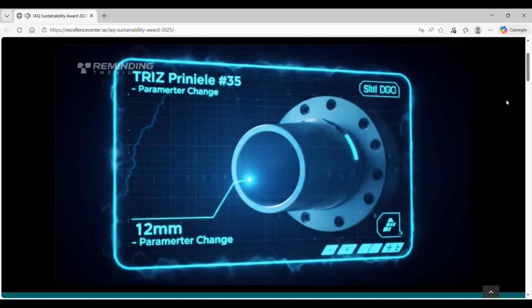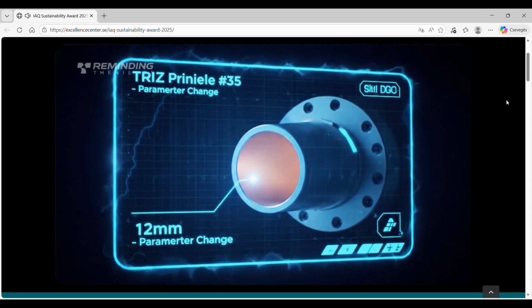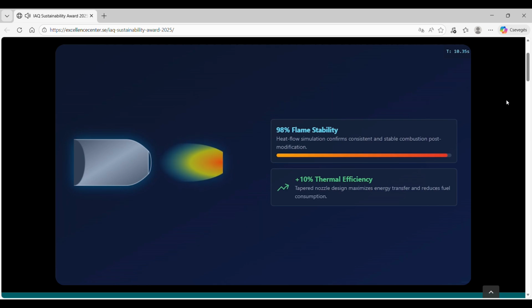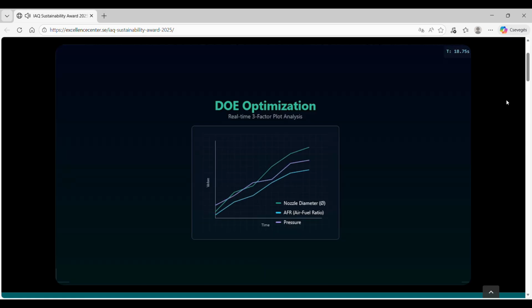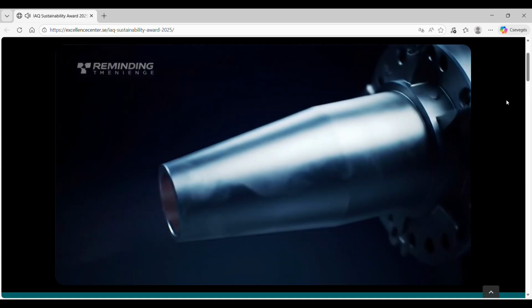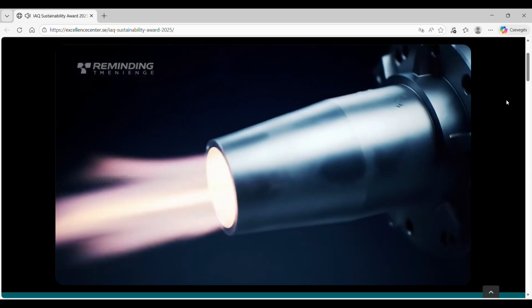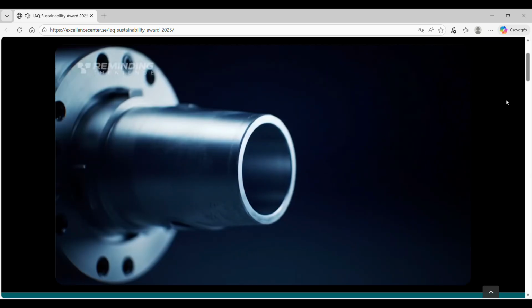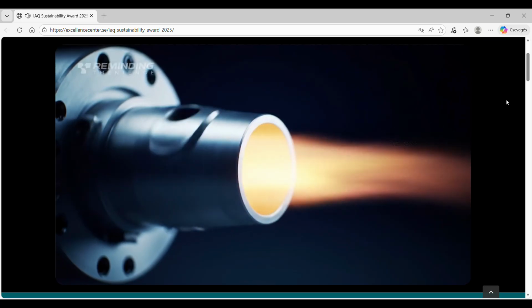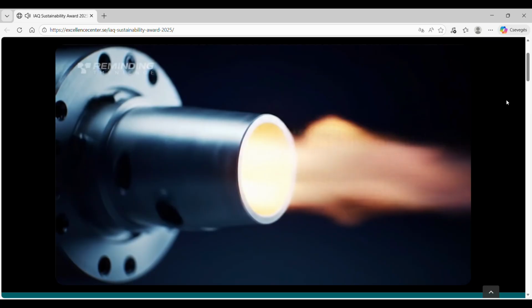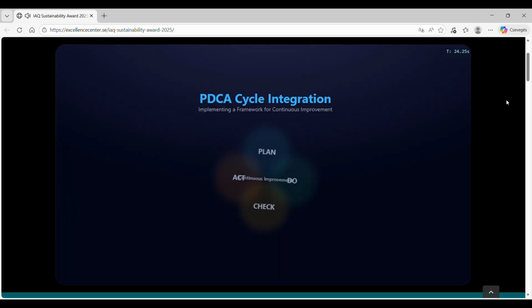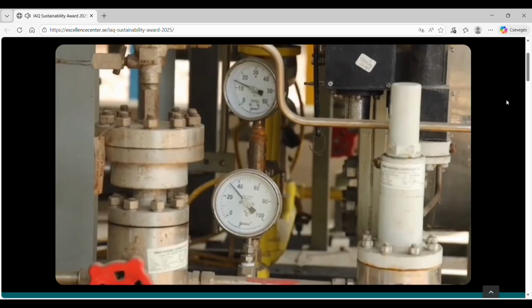To solve contradictions, we applied TRIZ, using Principle 35 to redesign a 12mm tapered nozzle, achieving 98% flame stability and a 10% increase in thermal efficiency. Using design of experiments, we optimized air-fuel ratios and pressure levels, reducing CO emissions to below 68 parts per million. Through Six Sigma, we controlled CO2 intensity to 0.005 kilograms per kilogram of fuel, within a tolerance of plus or minus 0.5%. And with 12 PDCA cycles, we achieved flame length consistency within plus or minus 2% at 150 millibar.